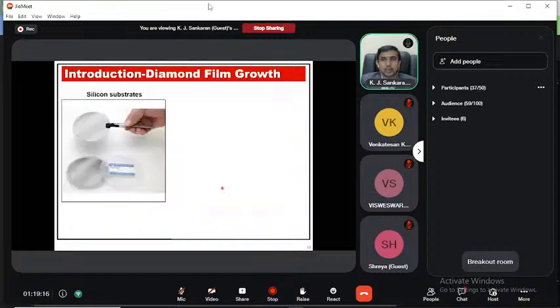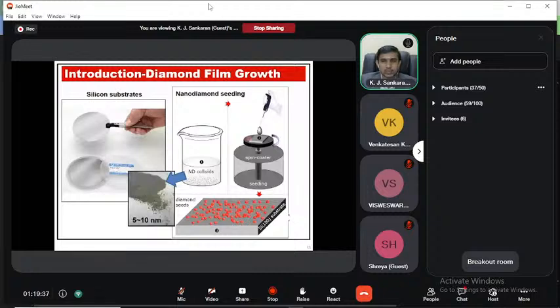Before going to microwave plasma CVD synthesis, we need a substrate to grow the diamond. For electronics and electrochemical applications, the substrate should also be conducting. So people go with the silicon substrate because most electronic instruments use silicon. This is the commercially available silicon substrate. Then we dice it into small pieces. So this is the diced silicon substrate. There we use a spin coating process to nucleate, because silicon contains no carbon. The spin coating suspension has nano diamond colloids with 5 to 10 nanometer diamond particles, which will be spin coated on this silicon substrate. So this is the silicon substrate seeded by the nano diamond particles.